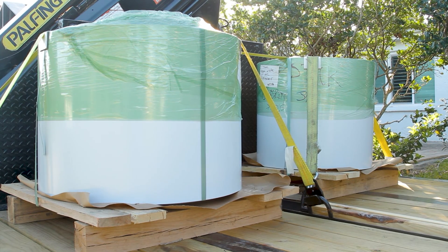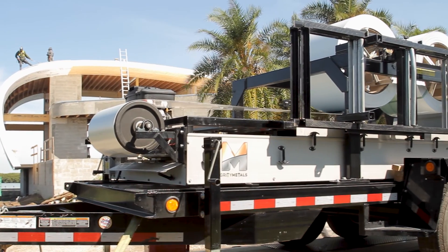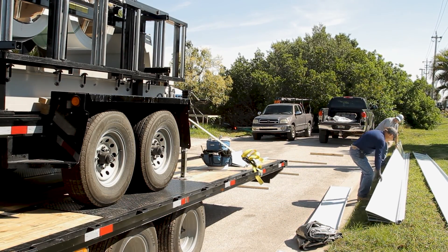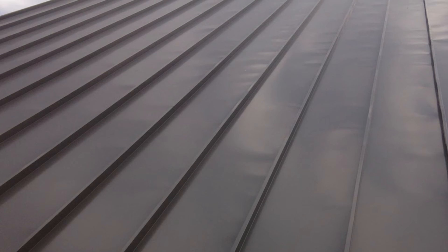A lot of the defects in our world are shape issues. That shape issue can cause problems downstream when slitting, or even further downstream when customers are fabricating a trim piece. If they put a sheet in a shear and want a nice long 10-foot piece, shape issues could cause problems and ultimately not end up with the best looking finished product. Similarly with rolling panels, if that memory in the metal isn't taken out and you're subjecting it to additional pressures forming trim or a panel, it's still going to want to keep that shape — it might show up in the form of oil canning.